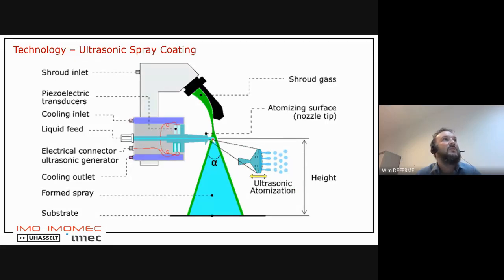But of course, if you generate droplets by just atomizing the surface, you will create droplets that have no or limited kinetic energy. So they do not move towards the substrate unless only by gravitation. So that's why we have this system here, where you have your shroud gas that is injected here, and that takes these droplets with a specific gas pressure towards the substrate. And that's the way it works. And then, of course, depending on the distance between the nozzle and the substrate, depending on the shroud gas itself, depending on a lot of parameters that I will talk about, you can define the angle and the width of impact of these droplets onto the substrate. So that's something to talk about somewhat later.